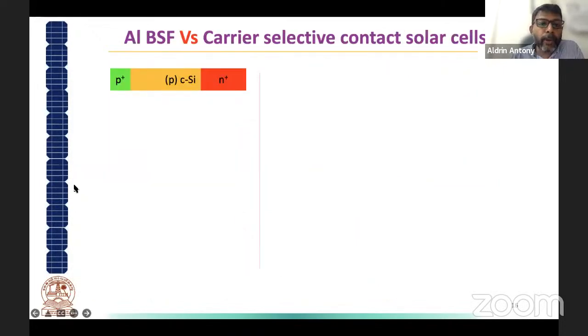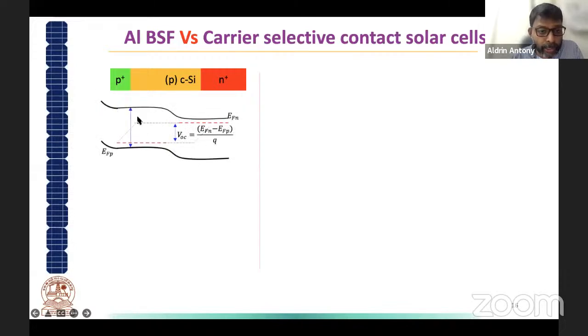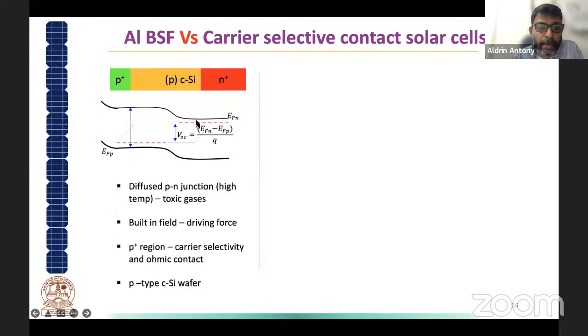And so if you look into an aluminum BSF versus a carrier selective solar cell, you have a crystalline silicon solar cell, a crystalline silicon here, one side will be N plus diffused, and the other side will be P plus diffused. And this is the band structure which I have shown earlier. And this is a thermally diffused p-n junction.